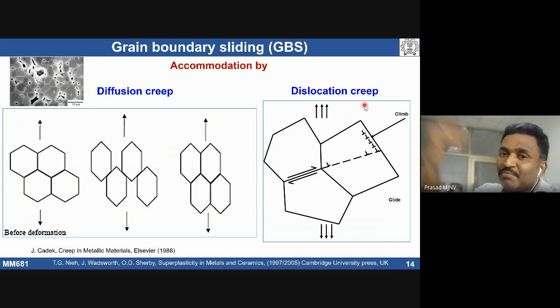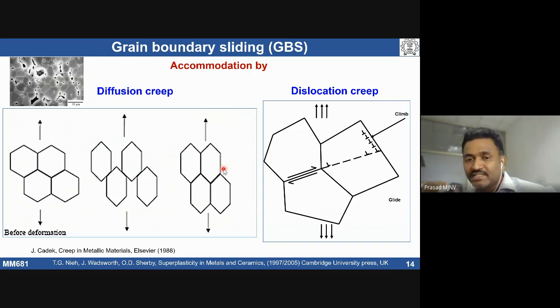Once you go to high temperatures, you can see dislocation activities like climb and cross slip, or diffusion activities can take place. So one of them can accommodate your sliding activity. Accordingly, we do see shape change in the crystals, in the grain structure.